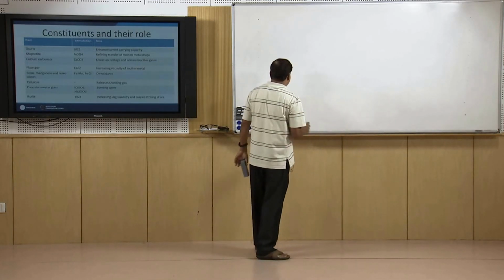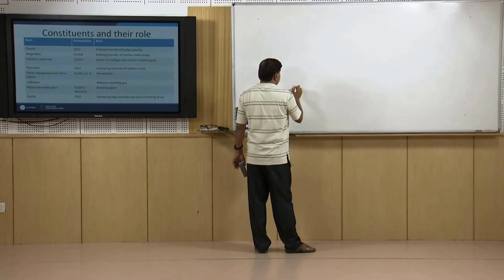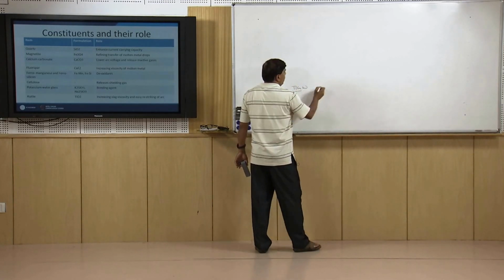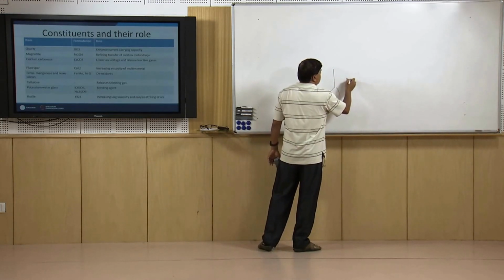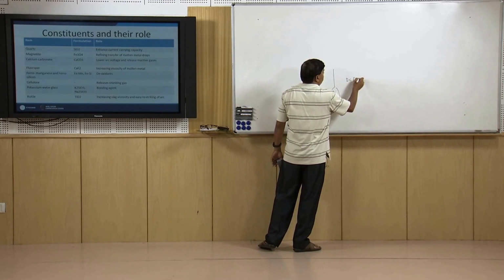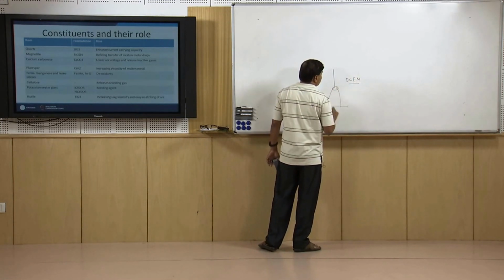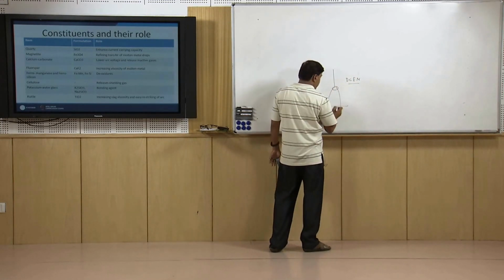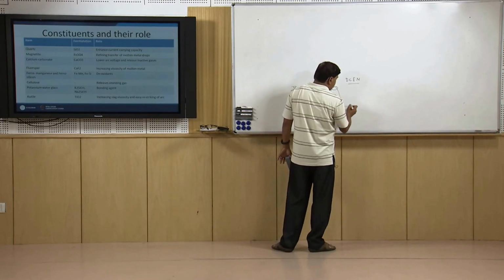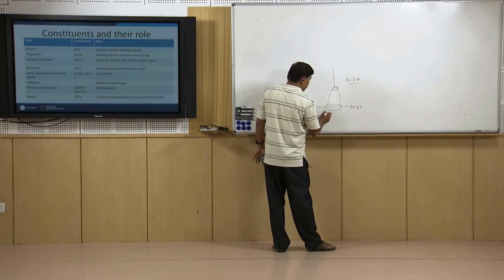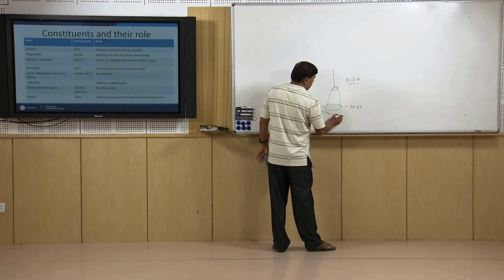If we see the process like TIG welding or GTAW process, the use of straight DCEN polarity produces less heat at the electrode and more heat in the workpiece side, while if DCRP is used, we get much better cleaning action.